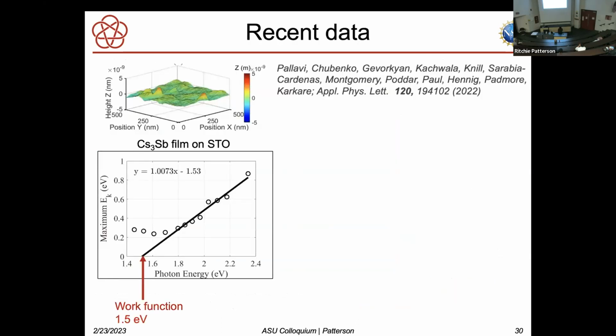Here is a photocathode that was grown through co-deposition, and here they have been able to plot the maximum kinetic energy as a function of the incident photon energy from the laser. And what that shows is that the work function for this material, which is one that's been studied a lot, is at about 1.5 electron volts. That's quite a lot lower than previously thought. And it suggests that maybe when people were making the MTE measurements, they were looking out here rather than right at threshold.